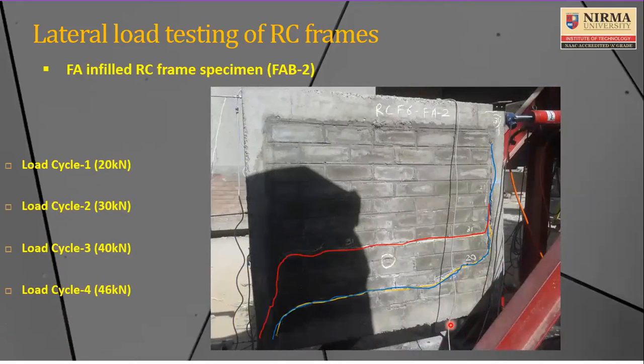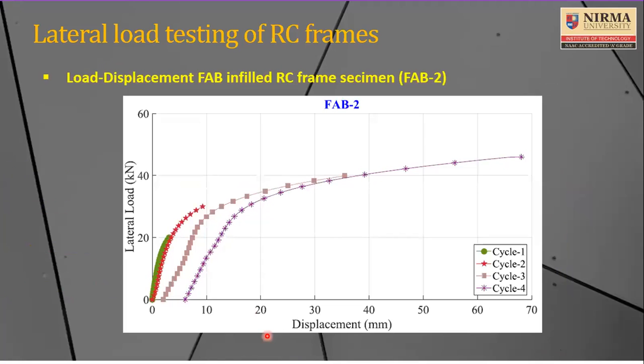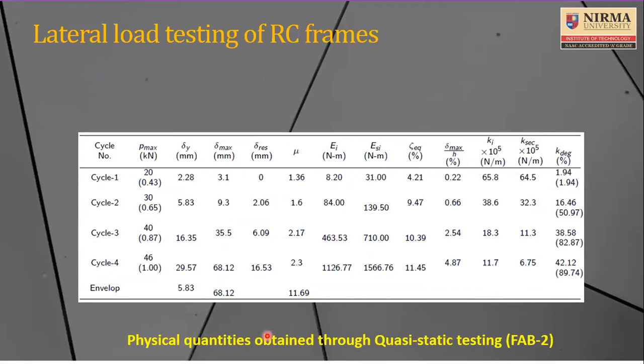Again you will find a very similar kind of failure: complete bed joint failure, through brick failure, vertical joint separations under lateral loading. All those typical failures that we have studied from various other literature have also been captured in our own experimental setup. And this is the load versus deformation cycle, and these are the various response parameters that we have obtained from the experimentation: the percentage of drift, as well as the percentage degradation or percentage reduction in the infill stiffness, as well as the equivalent damping ratio.